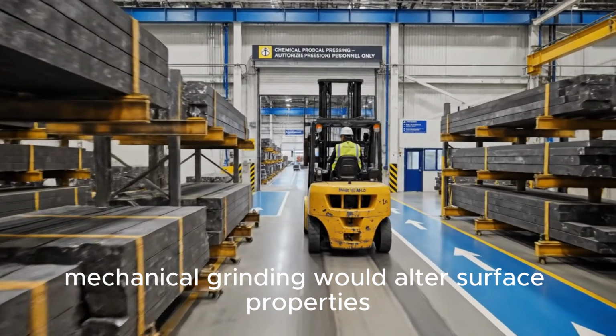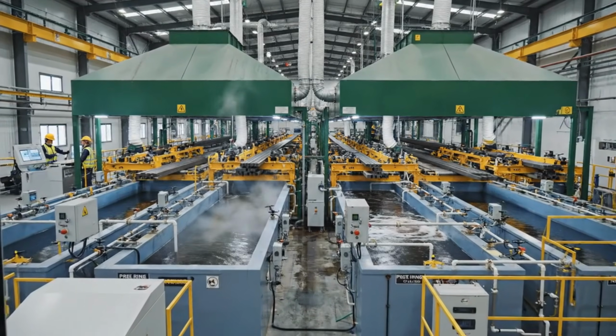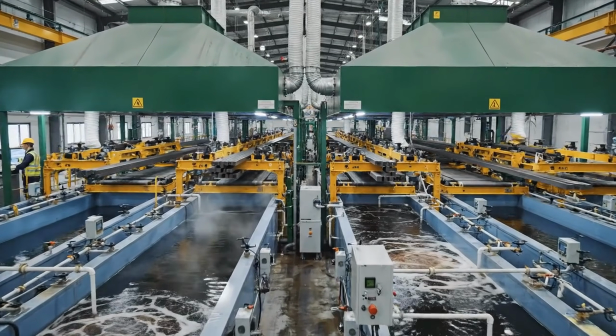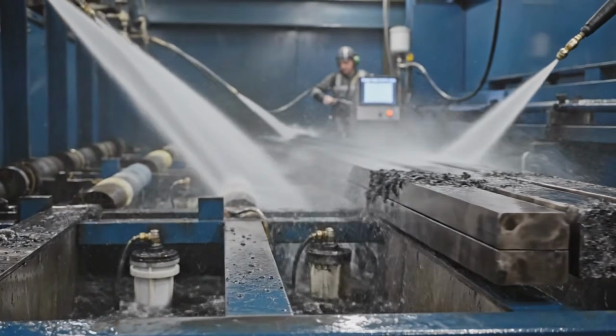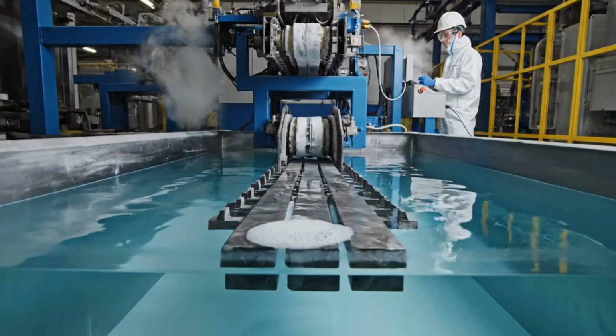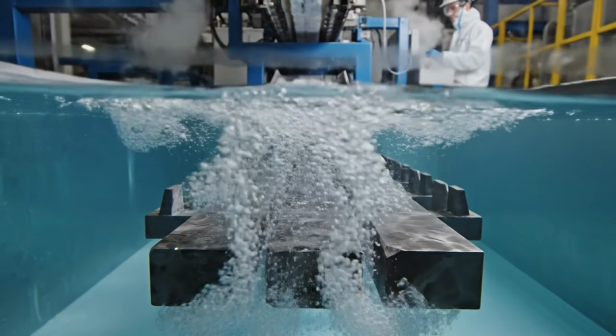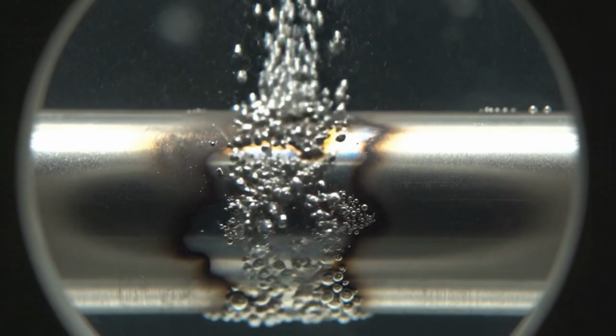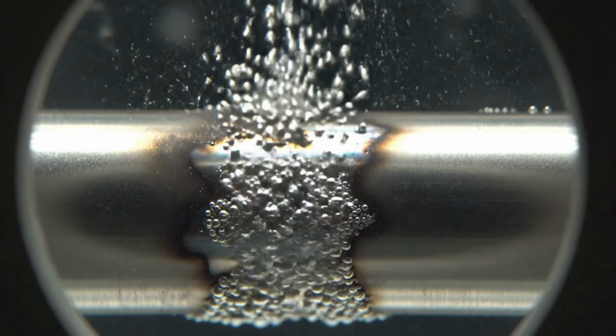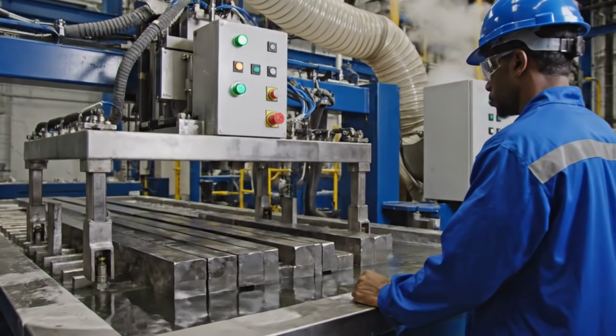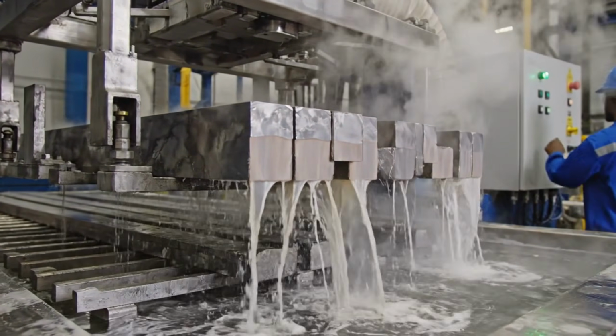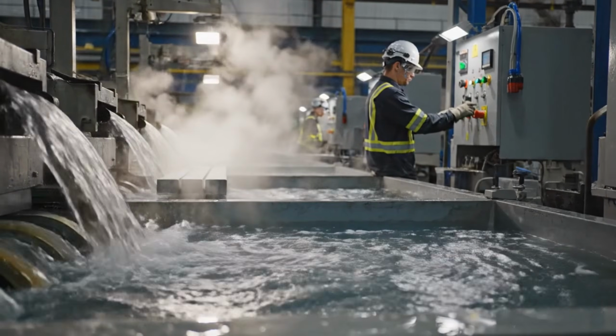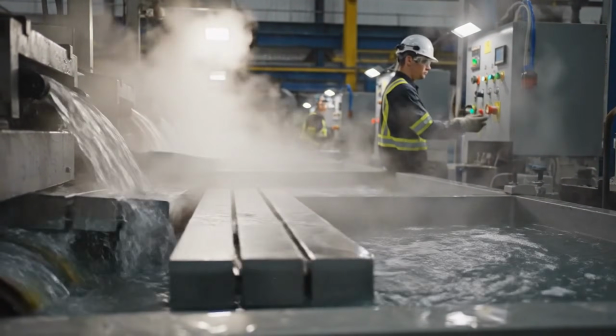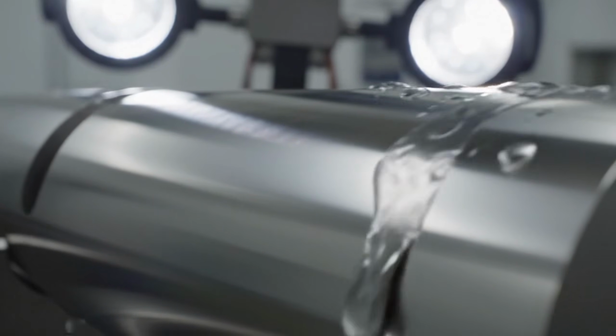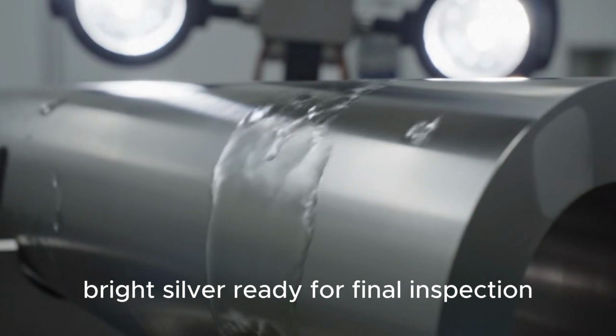Mill scale must be removed chemically. Mechanical grinding would alter surface properties. Too short, scale remains. Too long, surface pitting. Timing is critical. The finished surface, reactive titanium, bright silver, ready for final inspection.